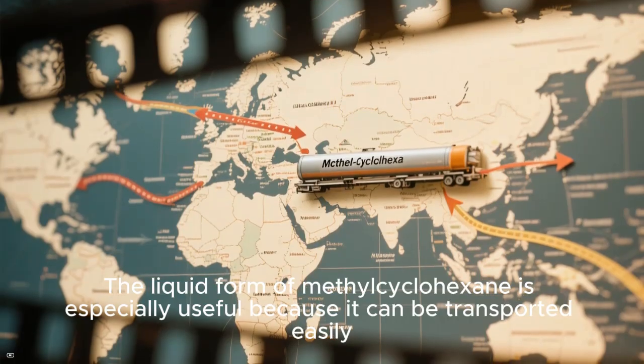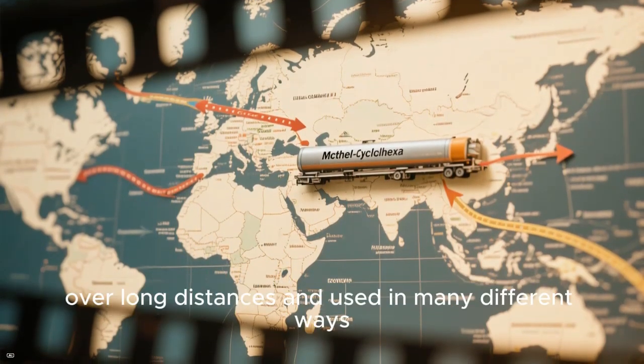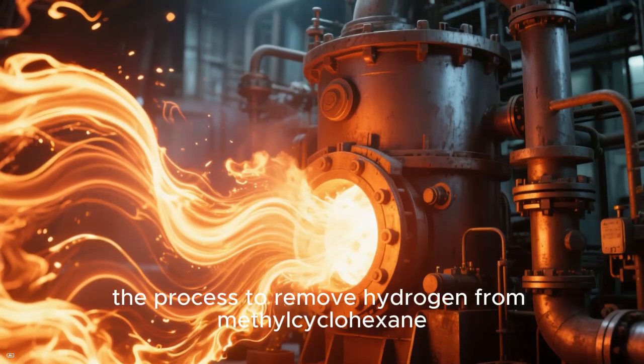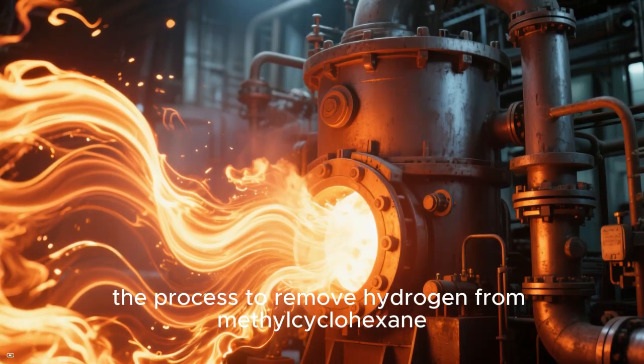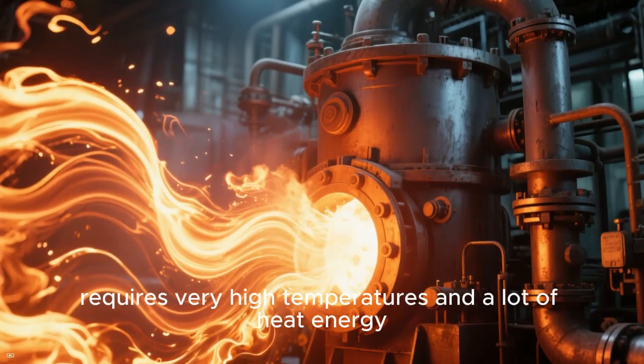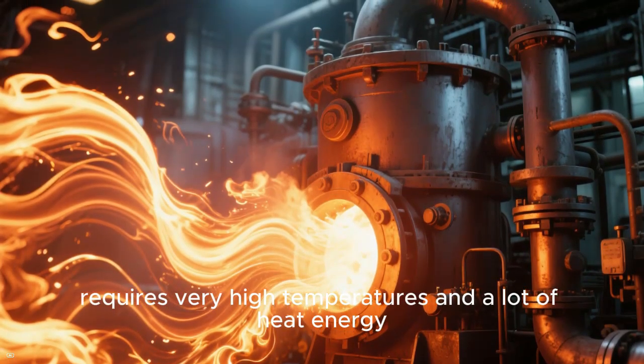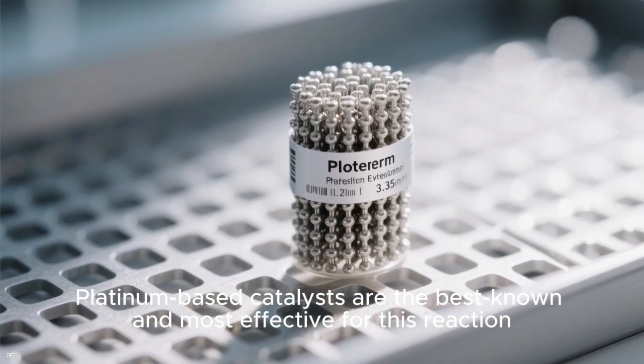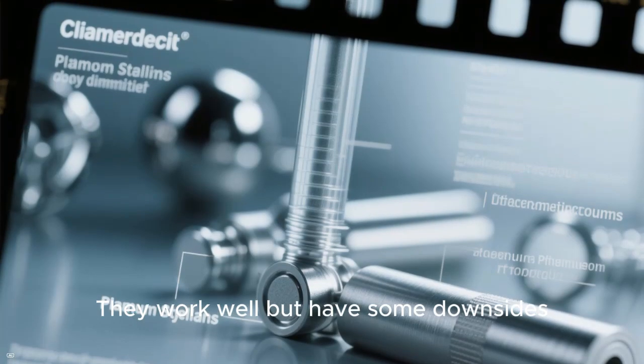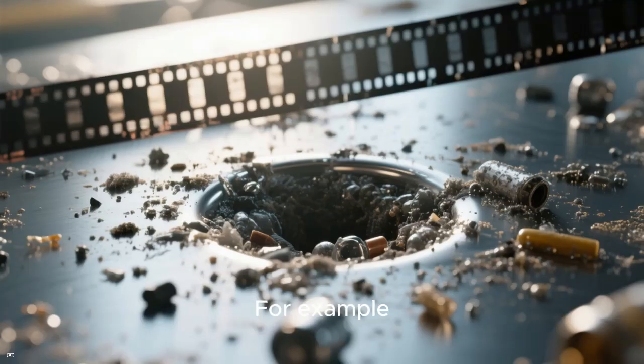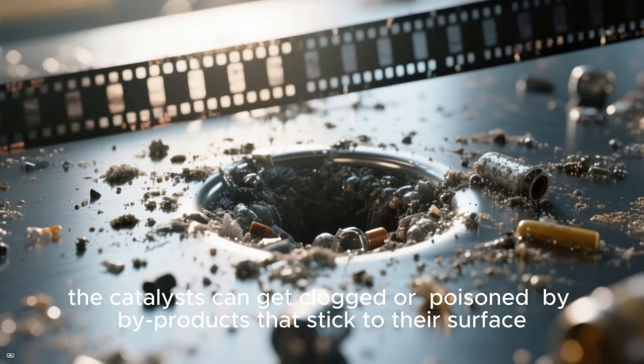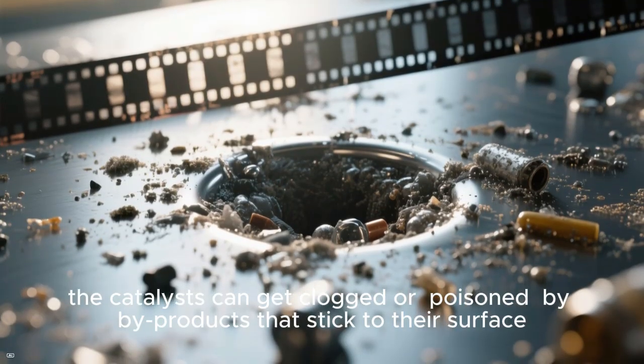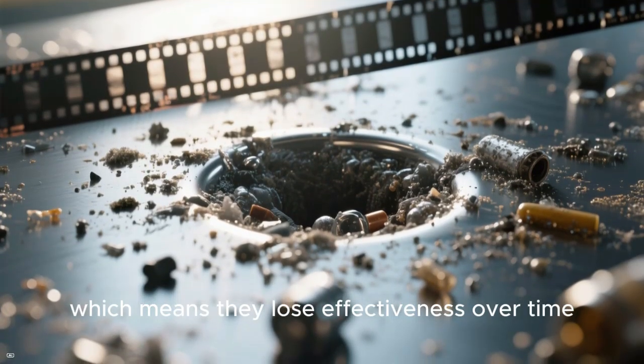The liquid form of methylcyclohexane is especially useful because it can be transported easily over long distances and used in many different ways. However, the process to remove hydrogen from methylcyclohexane, called dehydrogenation, requires very high temperatures and a lot of heat energy. This makes the process challenging. Platinum-based catalysts are the best known and most effective for this reaction. They work well, but have some downsides. For example, the catalysts can get clogged or poisoned by byproducts that stick to their surface, which means they lose effectiveness over time.